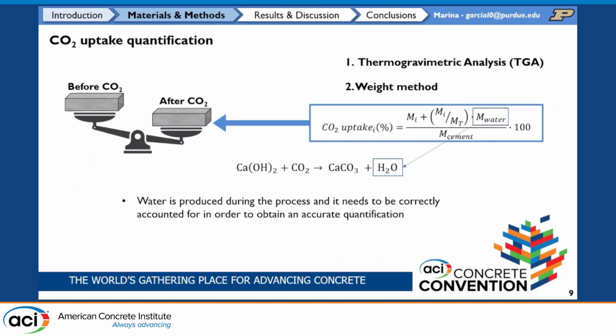Another method is the weight method, which basically accounts for the increasing weight due to the change from calcium hydroxide, in this case, to calcium carbonate. It has a bigger mass, and therefore you're increasing the weight of the sample. The only issue with this method is that because the reaction also produces water, you have to account for that water, and it's sometimes a little bit difficult to estimate.